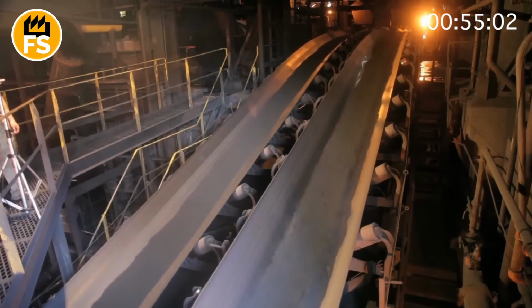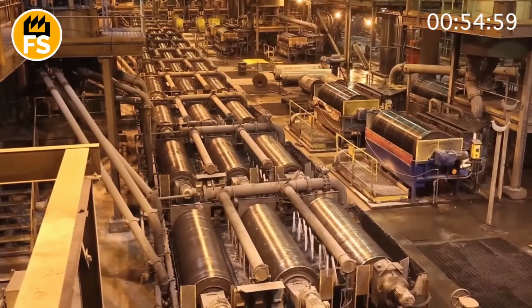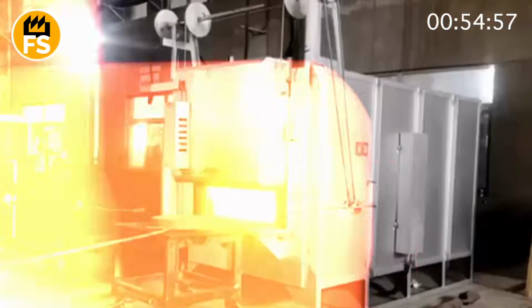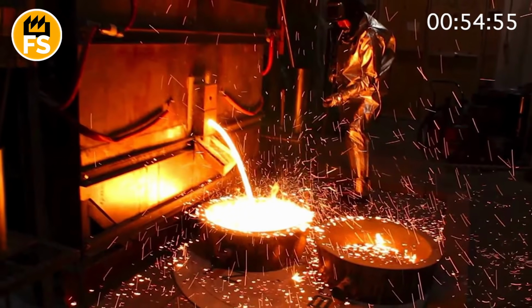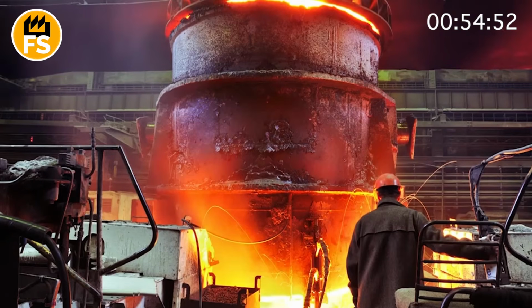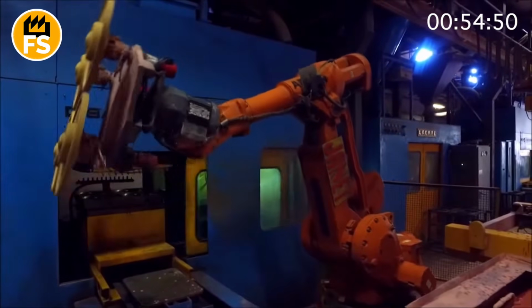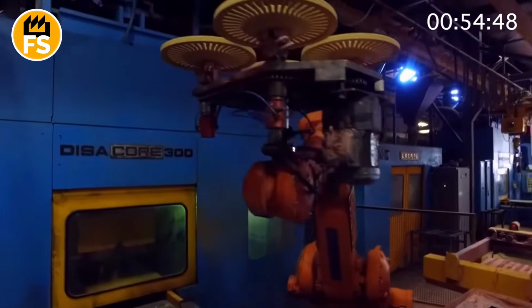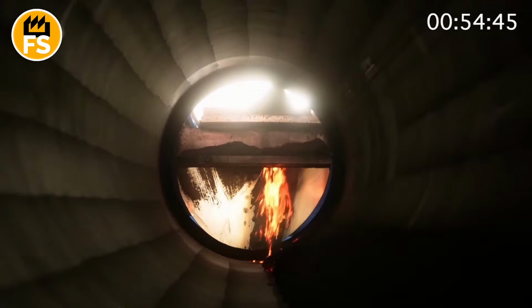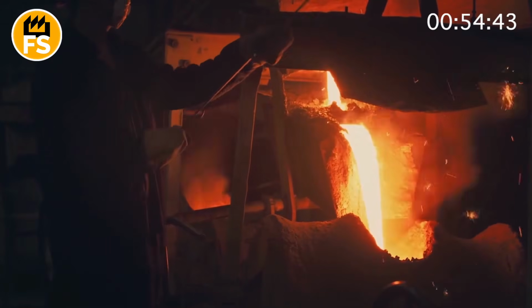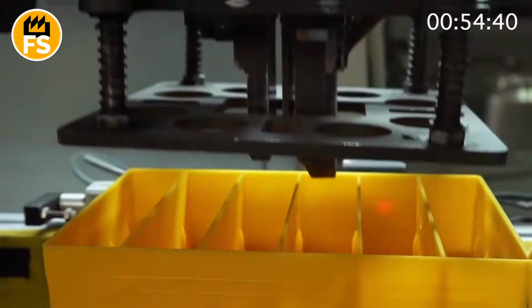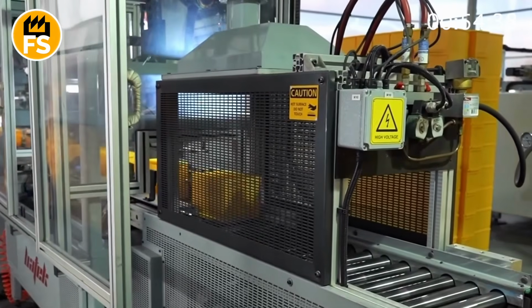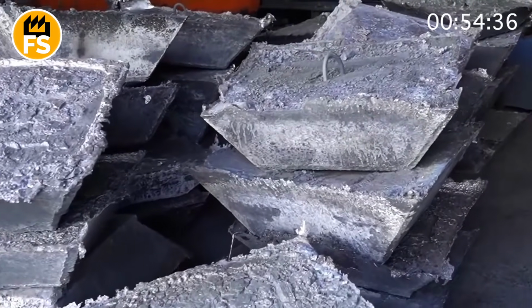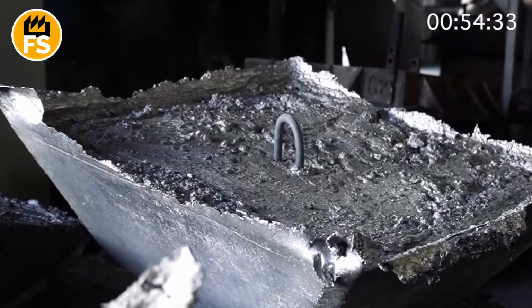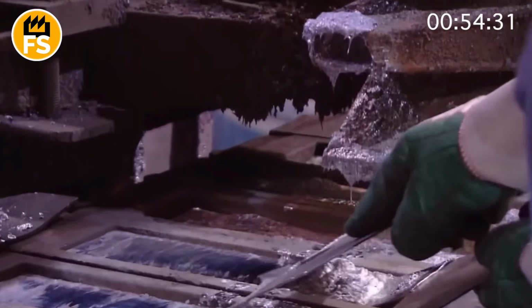Most often, gravity die casting or high-pressure die casting are used for head production. In the first case, the molten metal flows by gravity into a metal mold that can withstand several thousand cycles. In the second, the molten metal is injected under pressure up to 10,000 psi, ensuring precise filling of even the smallest channels. The mold, made of high alloy steel, is preheated to 400 degrees Fahrenheit or more to avoid thermal shock. The metal is supplied from a ladle or through an automated continuous feeding channel.